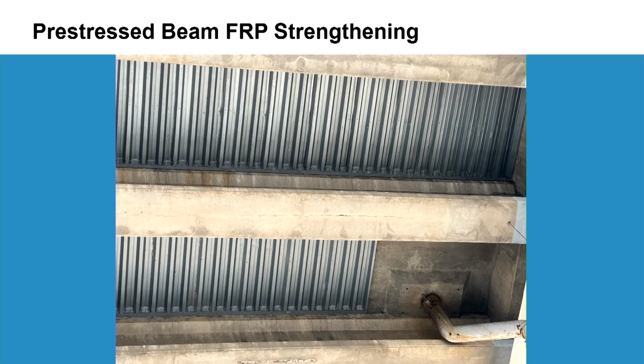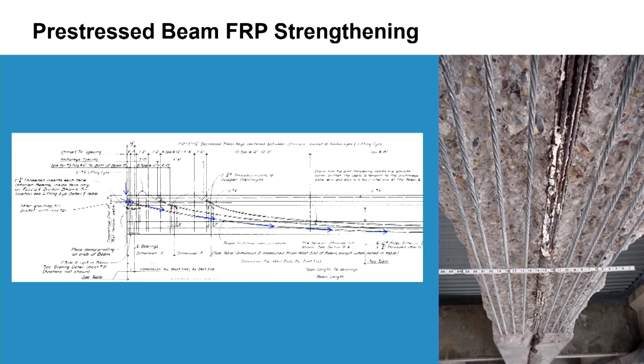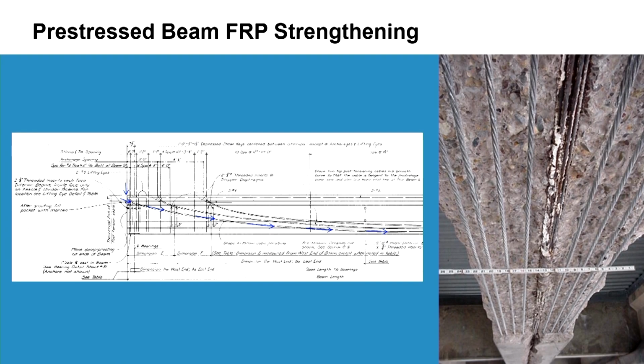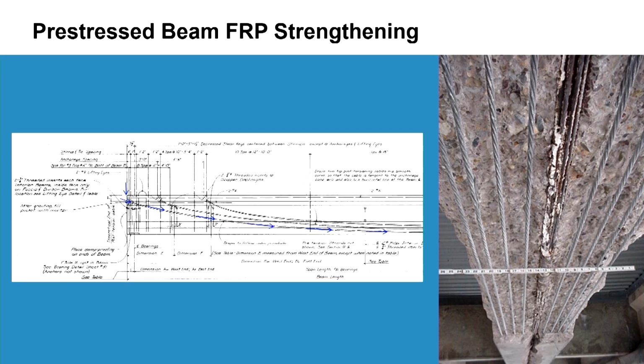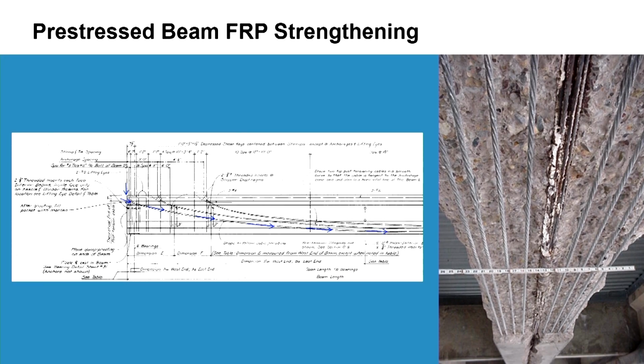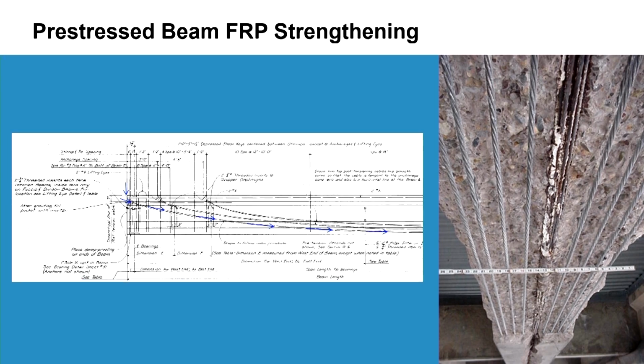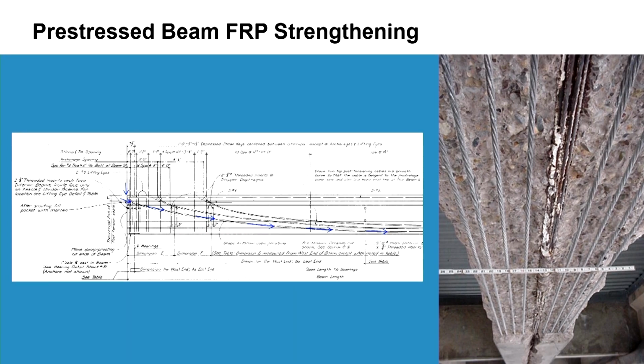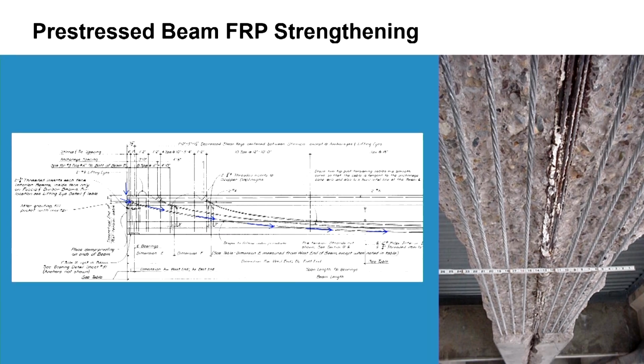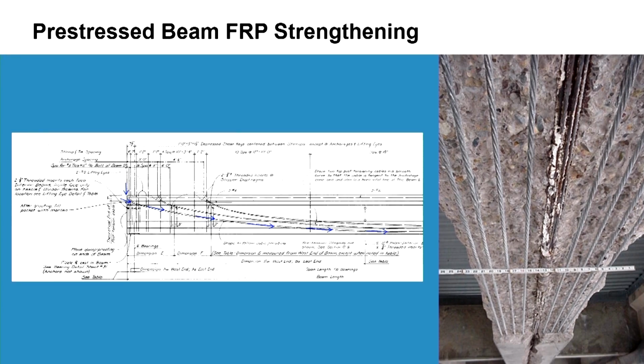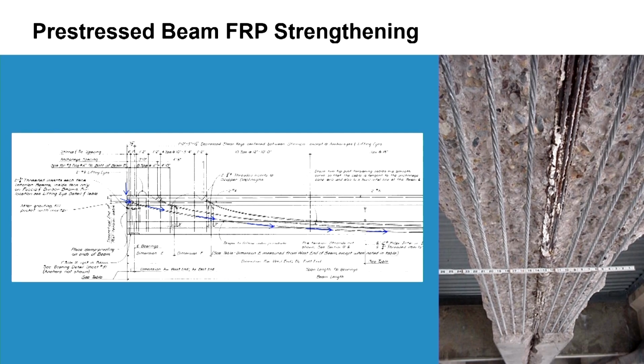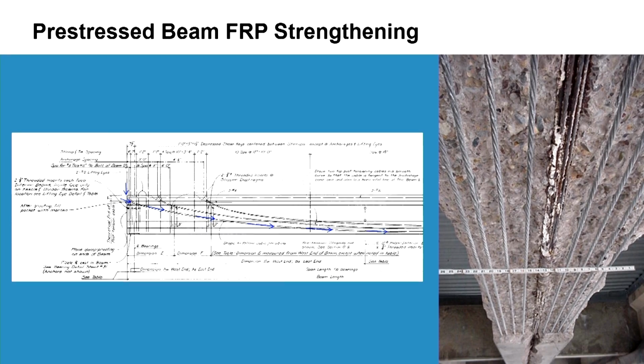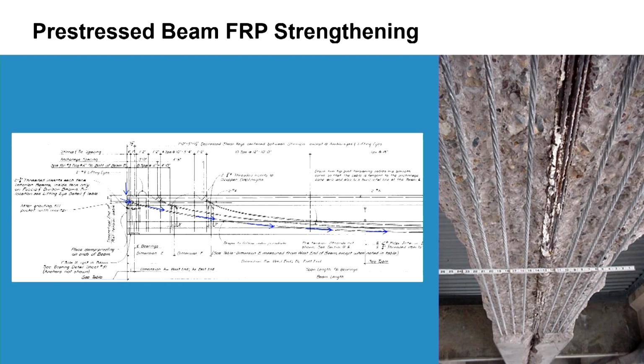Ahmad mentioned the longitudinal cracks in the bottom of the pre-stressed post-tension beams. These started developing about 20 years ago, and at that time, DDOT explored by removing the bottom of one of the beams to see what was going on. And what they discovered at that time was that the concrete itself, as well as the pre-stressing strands, were in pretty good condition. But as you can see from the top photo, that post-tensioning duct has a lot of corrosion, which, when that expanded from the corrosion, introduced the longitudinal cracks into the beams.